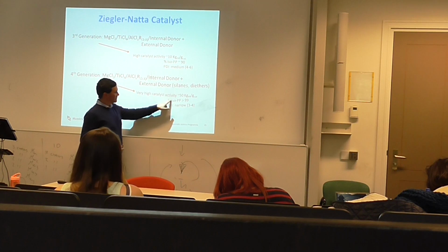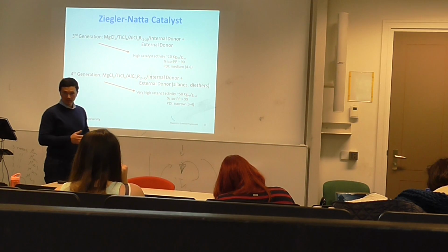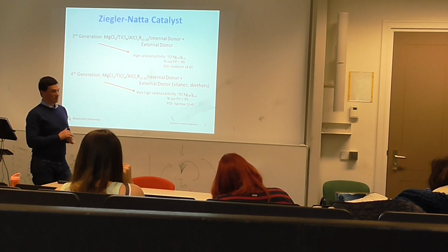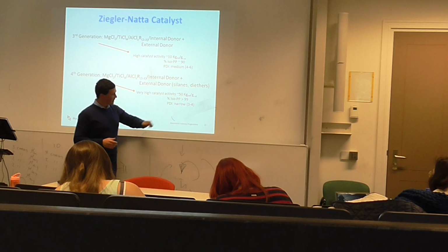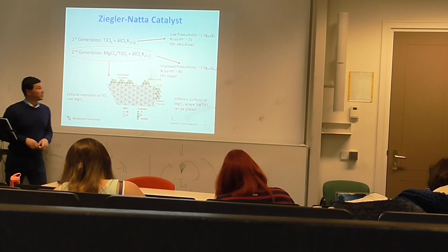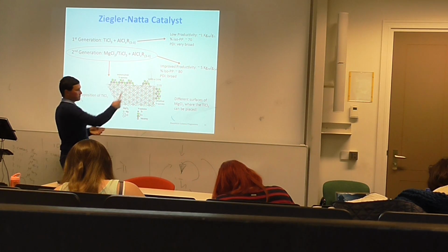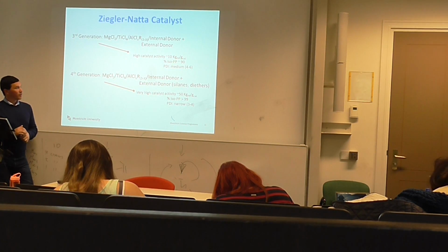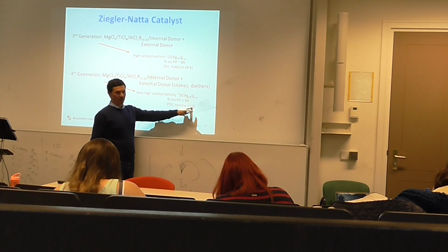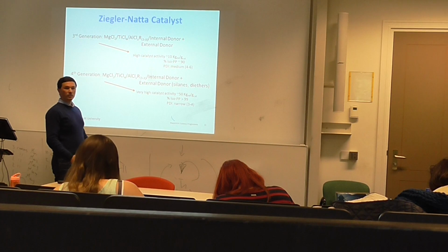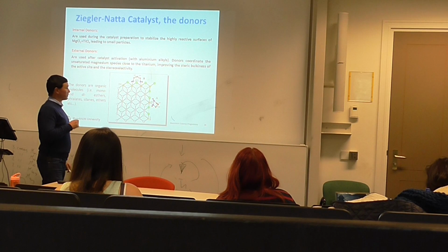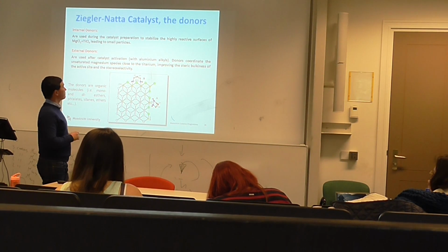Of donors can give this percent of isotactic index. 99% is extreme, almost fully isotactic, with a very narrow molecular weight distribution. So if we compare the molecular weight distribution, it goes from very, very broad, from medium and narrow. This is an exceptionally narrow molecular weight distribution for heterogeneous catalysts. Why? Let's see why. So this is the effect of the donors.